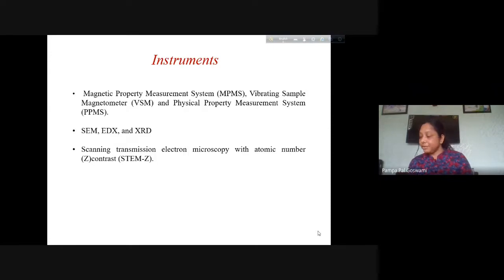The microstructure of the films will be characterized by the X-ray diffraction technique. So we can get the diffraction analysis, the XRD pattern, to determine the crystallographic structure of the material, and by using the EDX system we can microanalyze the chemical components of the systems we have prepared. Magnetic characterization can be done by vibrating sample magnetometer and also the SQUID magnetometer and also the PPMS system.